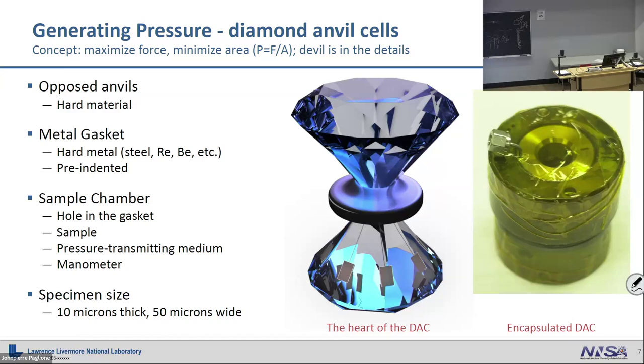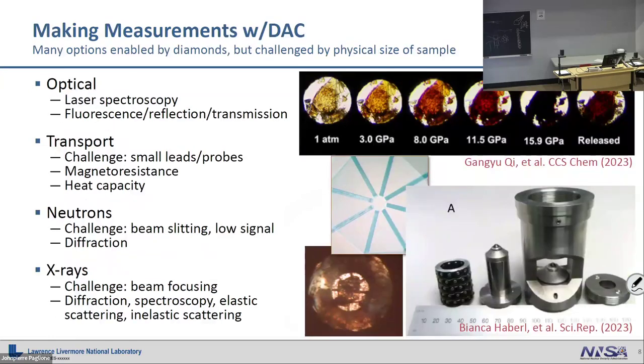DAC stuff is small. One of the things that Adam mentioned was a lot of people use needles. One of the first tools I ever used for loading my sample in a DAC was my own eyelash. So I had an eyelash, and I put it on a stick. And I kept that stick for like a decade, because if you look at your eyelash under a microscope, it'll be like 3 microns at the tip. It's a very pointy little thing, and it lasts a long time. So I don't encourage people to go pull all their eyelashes out routinely, but if you're ever stuck, you might have the tool right on your face.